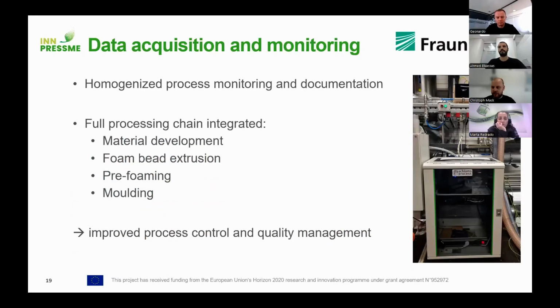And then the last upgrade was a very big one. We installed a data acquisition and monitoring system along the whole processing chain of the particle foams to homogenize our process monitoring and documentation. So we can now track the materials from the delivery to the final product and during characterization. And we have a tracking history with regards to process parameters, recipes, and also additional values from the environment, like temperature or pressure. And therefore, we can target the developments much more, also with regards to data-driven analysis.